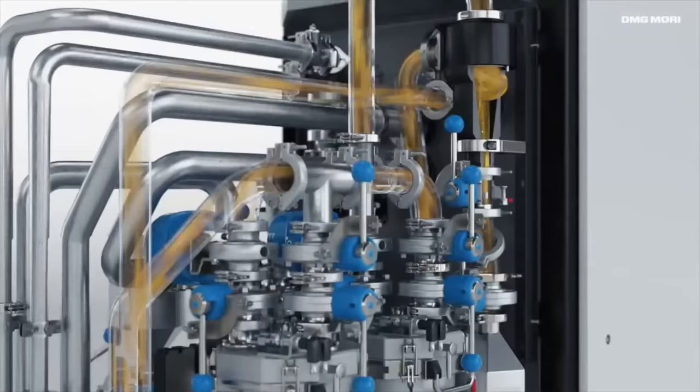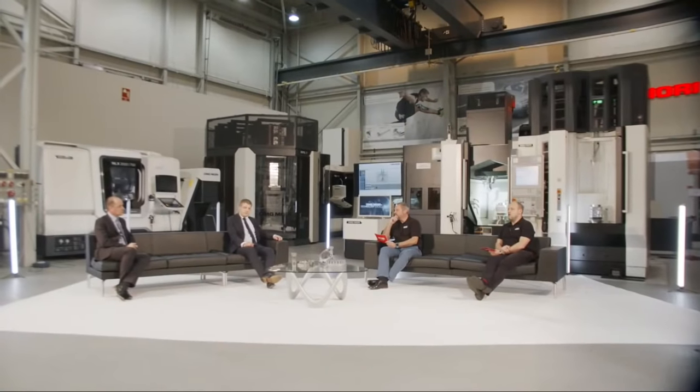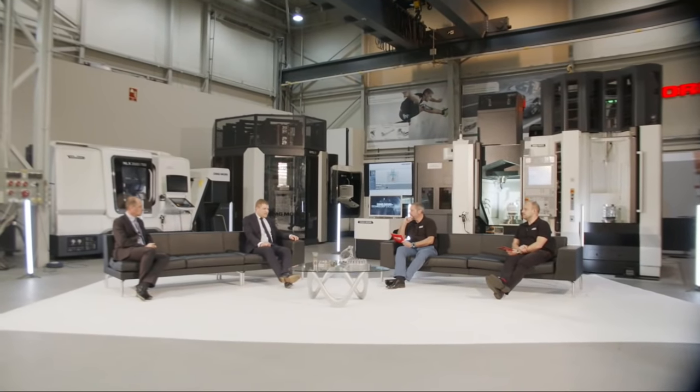There's quite a good question there, actually. Excited about this technology, what's the thinnest wall that can be printed, Terry? It's very dependent on the application, what you're building and how high that thin wall would need to be. What we have on the machine, the LaserTech 12 SLM, has a 35 micron laser spot. That's quite unique in the market in terms of thin walls and in terms of accuracy. And then on the dual laser machine, we're down to 50 microns on the laser spot.